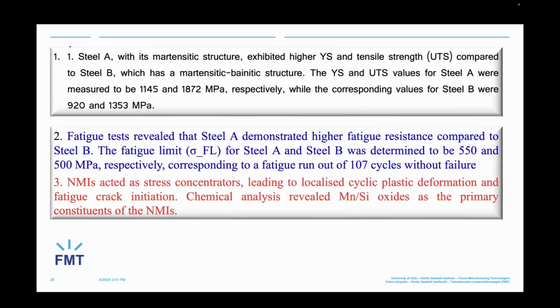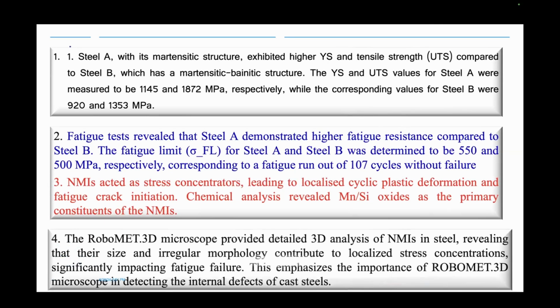Okay, this is the result, the conclusion. We found that non-metallic inclusions, because this is non-clean steel, act as stress concentrators for localized cyclic plastic deformation. It is the main reason for fatigue crack initiation.